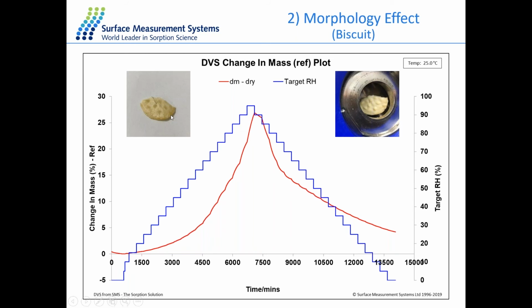And because the larger piece of sample is quite large, we cannot put the sample inside our sample pan. Then we can just use a very little piece of wire in the middle of this sample, and then we can put the sample directly on the hang-down wire inside the system or inside the sample chamber. And as you can see, the total experiment time is about 10 days, but still the sample mass didn't reach equilibrium almost for all the different stages. And this sample, the larger piece of sample, can pick up about 27% change in the mass at 95% RH step. But it can probably pick up much higher than that because it didn't show the equilibrium at all.